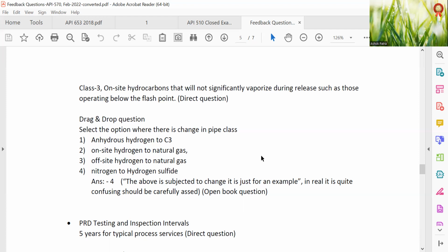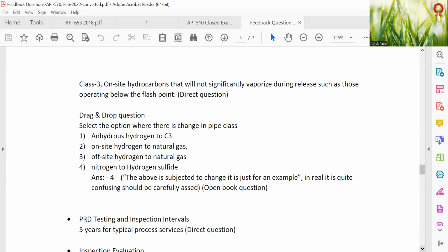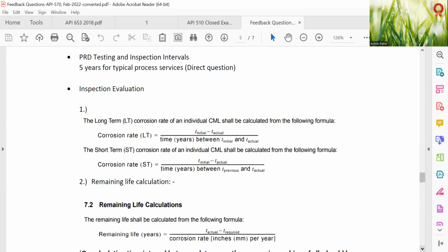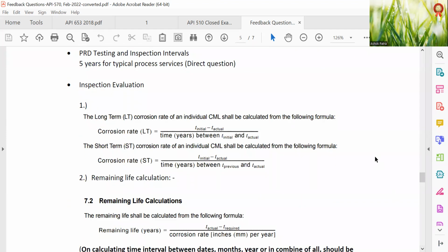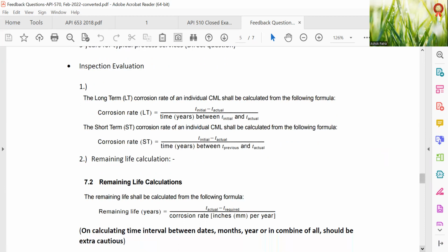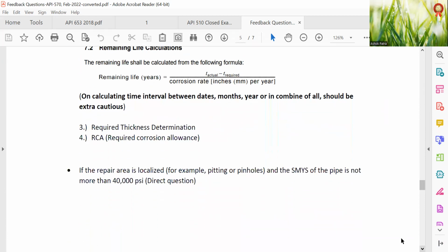Testing and inspection intervals: 5 years for typical process service. Direct question. Inspection evaluation: the long-term, short-term corrosion rate, remaining life calculation. Required thickness determination, RCA, required corrosion allowance. The repair area is localized, in the example a pinhole. The SMYS of pipe is not more than 40,000 psi. Direct question.